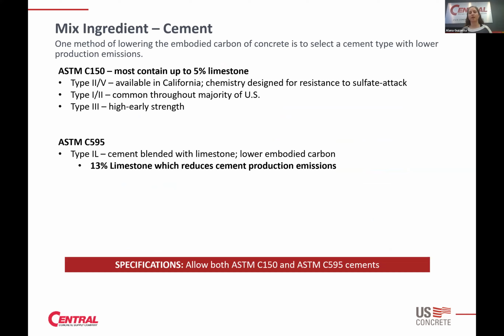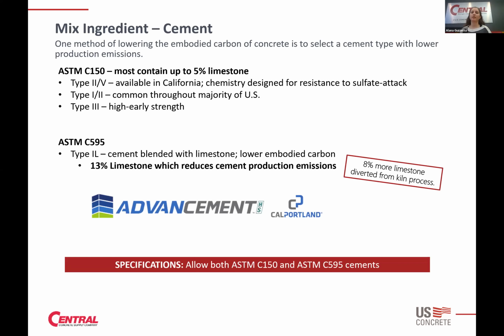And if you have a cement that meets C150, it can contain a 5% limestone. And so that limestone is talking about limestone that has not gone through the kiln and is blended in with the cement product that has been processed through a kiln. But a C595 cement is a blended cement, and so that allows for a higher amount of limestone. So you can get up to 15%. Commonly, we see cements having 13 to 14% limestone. And so what this does is it reduces the embodied carbon of your mix by about 7 to 8%. If you're taking a C150 cement and pound for pound replacing it with a C595 cement, that's going to result in about a 7% reduction in your GWP for the mix.